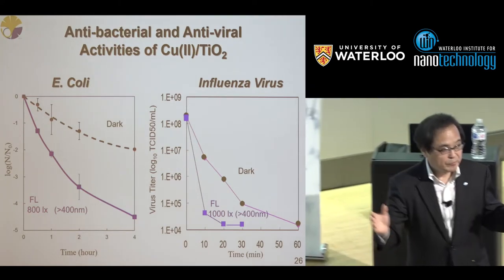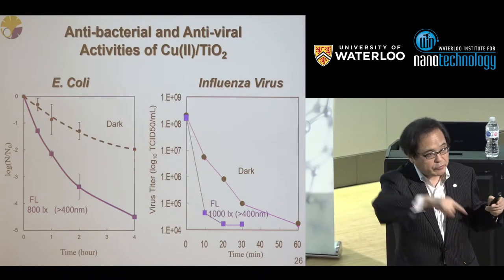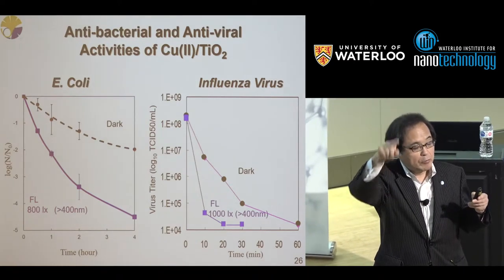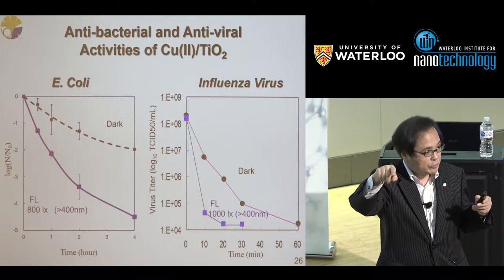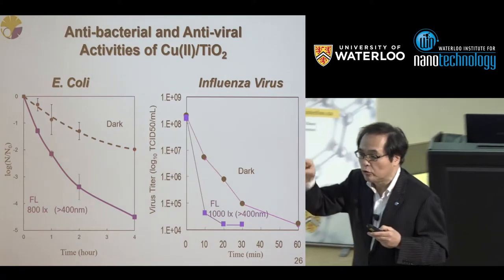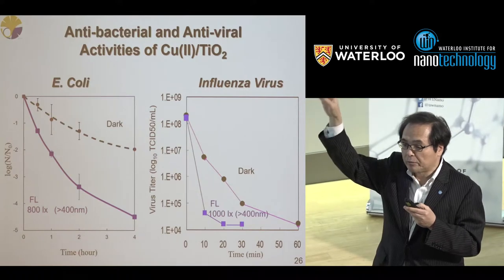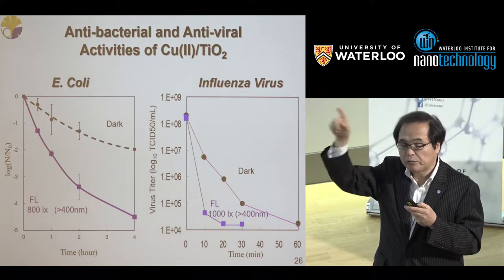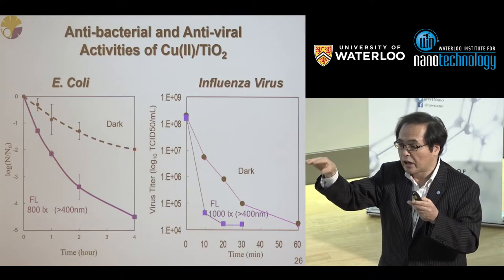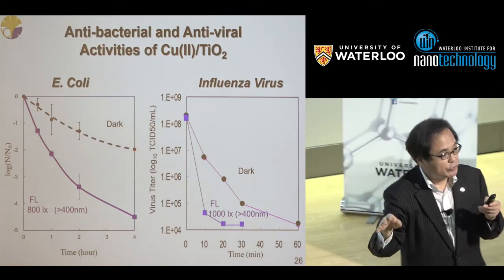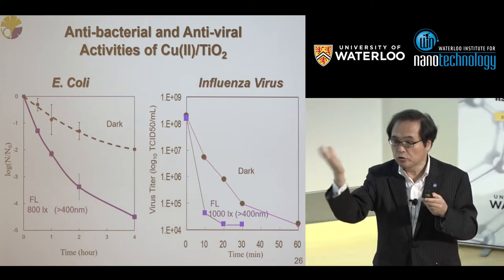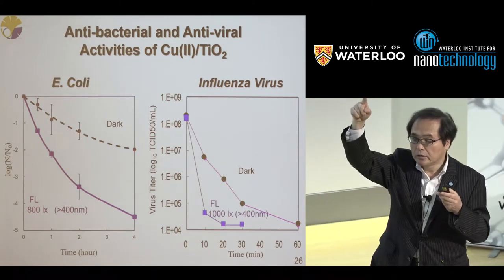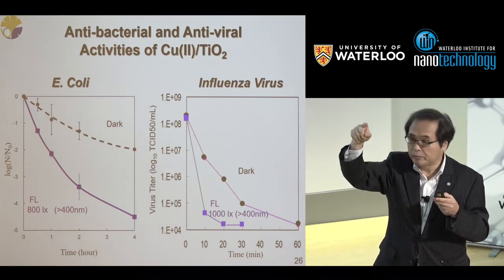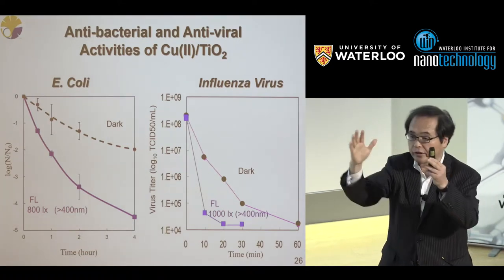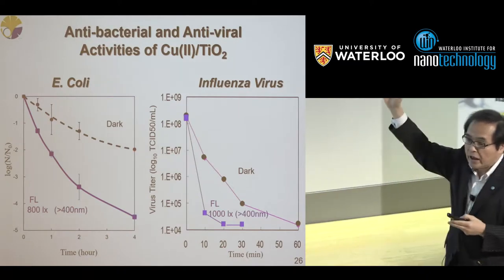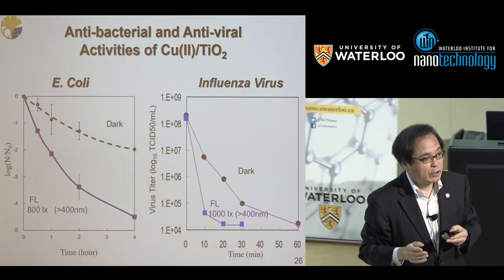The reason is, by the illumination of this charge transfer band of divalent copper, monovalent copper species is produced. And monovalent copper is known to have a very strong antibacterial, antivirus effect. However, monovalent copper is not stable under ambient conditions. That's why it cannot be used. But as I told, we can produce it by such photoillumination. That's why a certain amount of monovalent copper always exists on the surface. So it has such a very strong antibacterial, antivirus effect.